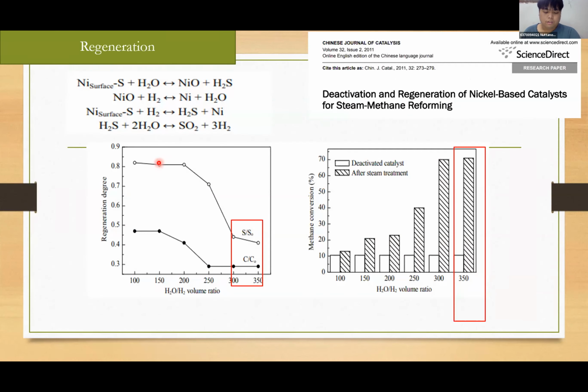The result from the study was shown in the ratio between sulfur content before and after regeneration. And when the ratio between steam and hydrogen increased, the regeneration increased too. It means to get back the high activity, a high ratio between steam and hydrogen is required. However, this process takes a long time to eliminate sulfur.